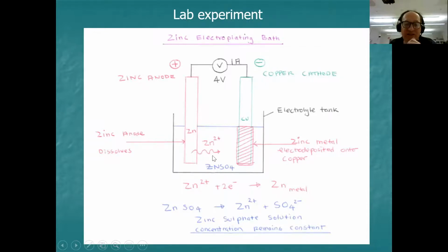It's important to understand that in this process, the only thing that's actually happening, the zinc is dissolving to form Zn2+, is traveling across the gap to where the copper is, and the reverse reaction's happening here, where the zinc ions are picking up the same 2 electrons they had a few seconds earlier and forming metallic zinc. So the whole turnaround process is just simply transferring metallic zinc from one side to the other via the intermediacy of this electron transfer process, which is why it is an electrochemical process. So this has all the features of electroplating in one simple operation, which you could easily understand. And that's why I set it as an exam question, in fact, because it is fairly straightforward.